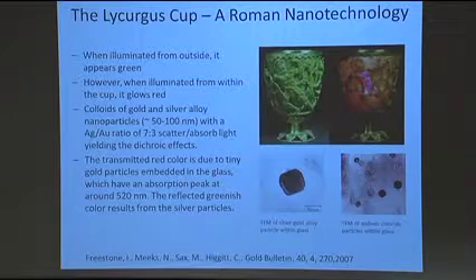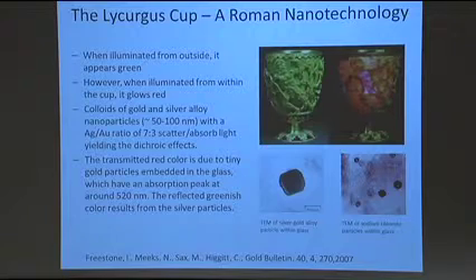And here, for example, is a picture of one of those particles that forms this colloid throughout it. And what happens then is that the silver in this nanoparticle is used in the reflection to reflect the green, whereas the gold actually transmits the red color here. And what's important here is this wouldn't have happened if I just added gold and silver at some large scale. It's really the fact that it's in a colloid form at this very small scale.